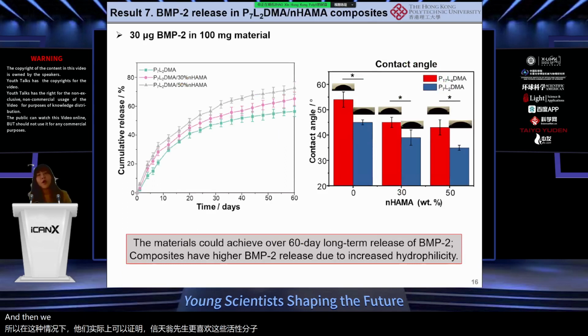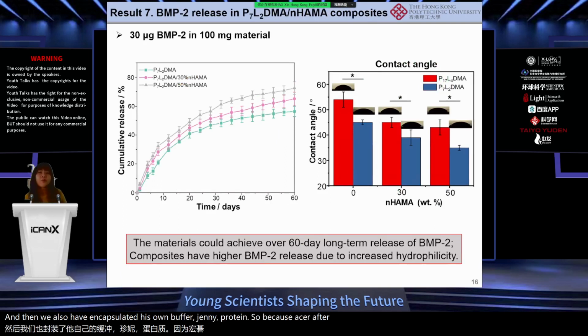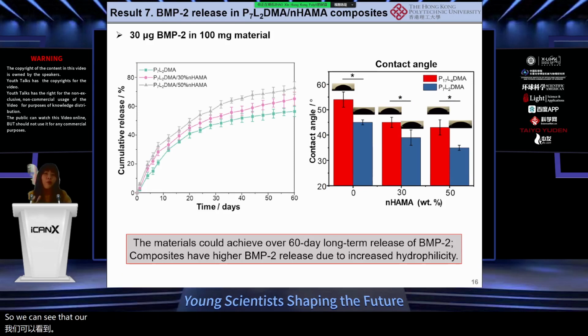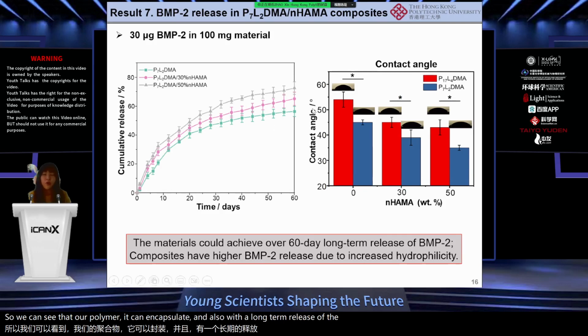And then we also encapsulate the bone morphogenic protein, because it's an FDA-approved growth factor for bone regeneration. So we can see that our polymer can encapsulate and also provide long-term release of the bioactive molecules.